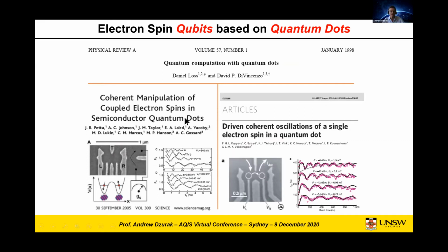So both of these papers were in gallium arsenide. This is a double quantum dot using gate electrodes to provide corrals for single spins to be located in potential wells. And they're able, via different techniques, to manipulate the spin. I'll come into spin manipulation again a little later. But as I mentioned, both of these were in gallium arsenide because that was the platform, because it has a very low disorder interface between gallium arsenide and aluminium gallium arsenide. And so these were low disorder structures that could give very nice potentials for the electrons to sit in.